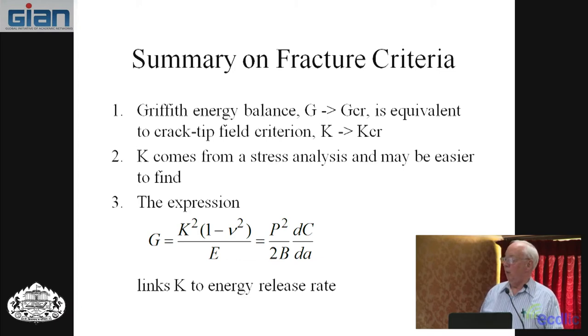However, when Irwin developed that approach based on stress, Griffiths also had the energy balance approach, and so George Irwin did this. He showed that the Griffiths term was related to the K. So whether you use the Griffiths approach or a K approach, you have essentially the same analysis. However, in most analyses, it's much easier to calculate stresses than it is energy. People use theory of elasticity or numerical methods to calculate stresses, and then it's easier to calculate the stresses.